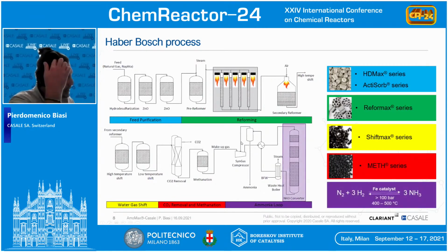And for this reason, this is an iron catalyst that was developed around 100 years ago, but was modified during the years. And what was modified also was the technology of the reactor. What is important is that the catalysts suffer from poisoning by oxygenates. So you have to protect the reactor like a baby and arrive with a few ppm of oxygen and other poisons at the main reactor, the syn loop.